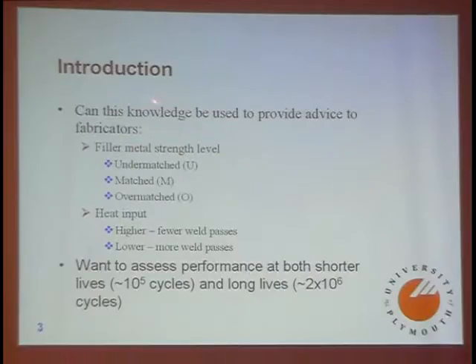And in principle, at first order, if one understood what residual stresses and microstructural changes did to welds, you might be able to provide some advice to fabricators. And this is actually quite useful advice if you can get around to it. Should they make welds with undermatched, matched, or overmatched filler metal to get particular properties? Should they use higher heat input with fewer weld passes or lower heat input with more weld passes? If you could even get that far, it would be quite beneficial.